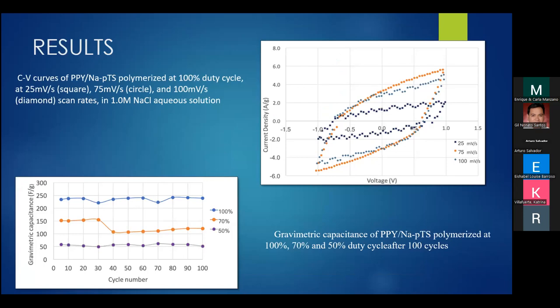Okay, and what else did we do? We also tried measuring the CV plot of the film at different scan rates. So the plot on the upper right shows the CV curves for the polymer that was synthesized at 100% duty cycle, because it is the good one, with high specific capacitance.